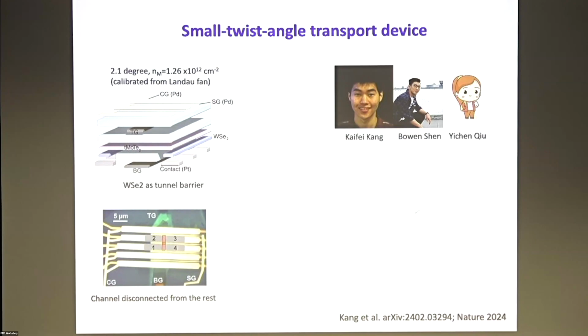And on top of the top gate, we actually pattern another series of gates. One of them is the contact gate, the CG here, which is to turn on the contacts. I'll tell you a little bit. And then the other one is the split gate. It's basically to turn off those regions that you don't want in the channel. So this is a picture of the device. We actually have more like an H shape for the device.